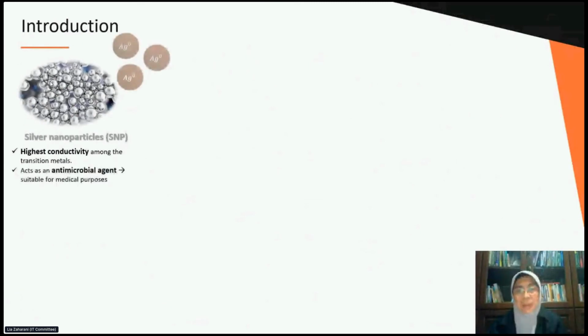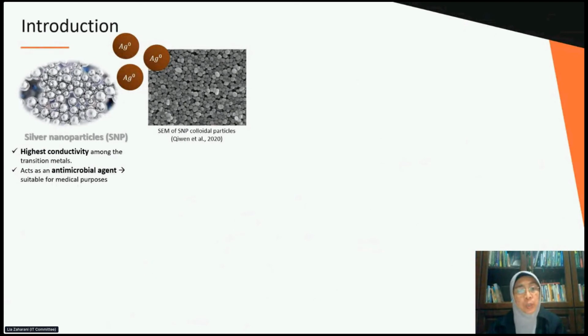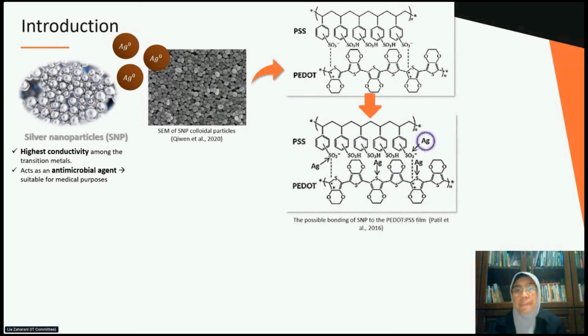Not just as an antimicrobial agent, this SNP can be another strategy to improve the electrical conductivity of a conjugated polymer through the incorporation of this nanoparticle into the conducting polymer. SNP exhibits the highest conductivity among the transition metals. It acts as an antimicrobial agent, as we mentioned earlier, making it suitable for biomedical applications. Since the electrode will be placed underneath the patient's skin, the PEDOT:PSS is able to absorb the moisture from the sweat. Meanwhile, SNP is able to prohibit microbial growth, and it's good for preventing pressure ulcers.